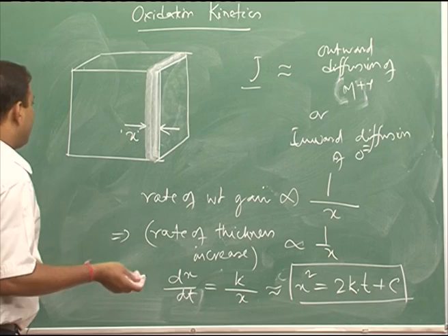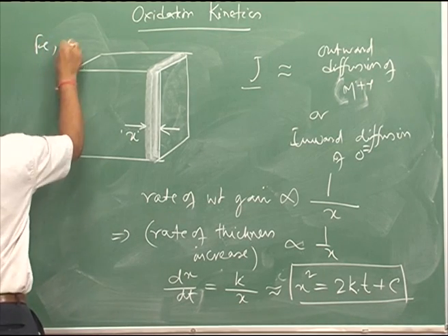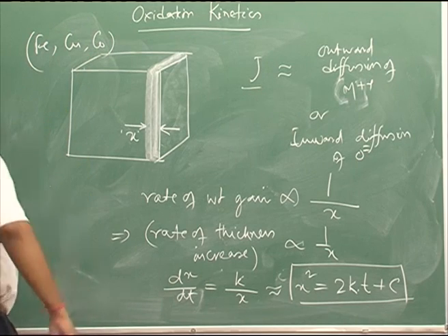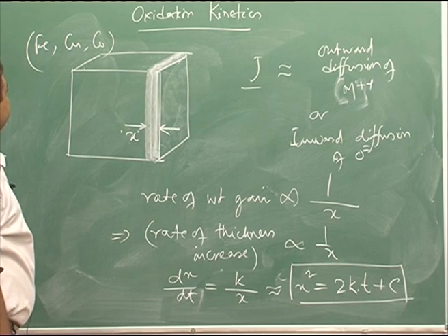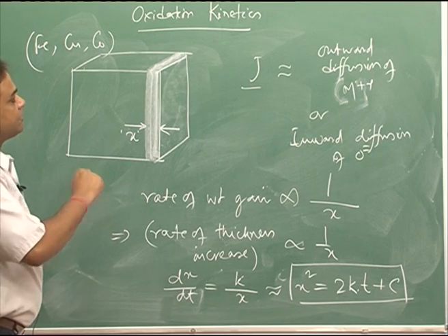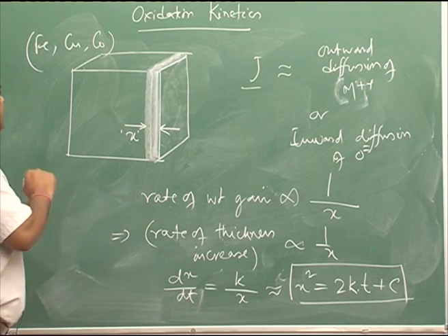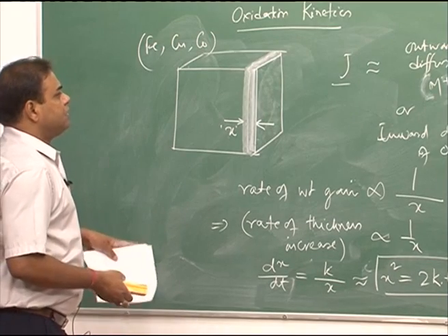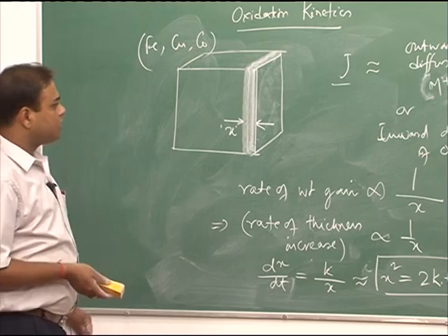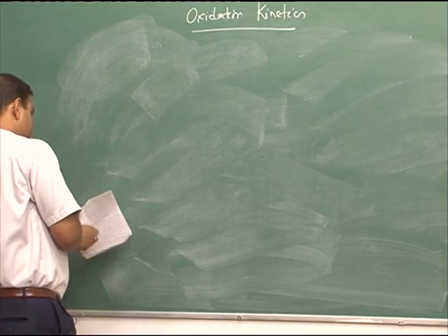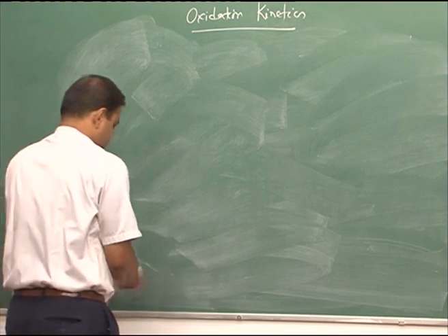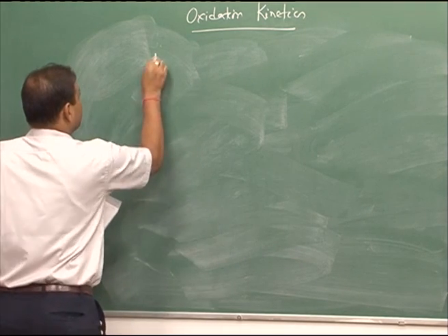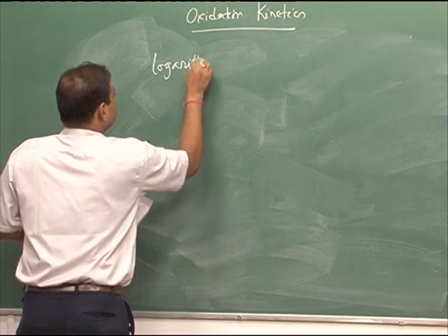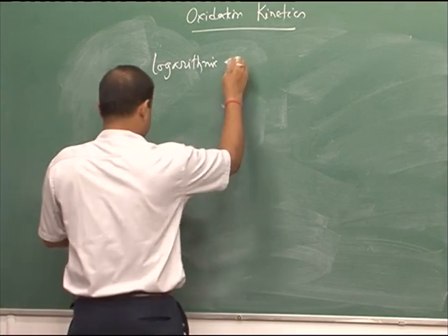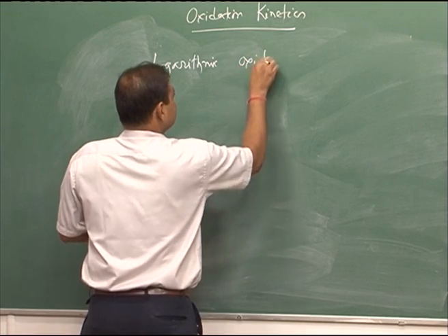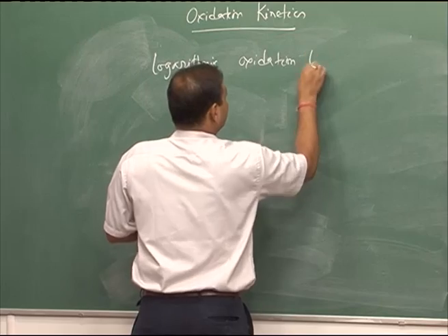So, this is a simplistic approach to prove the parabolic oxidation law, and where we can find this parabolic oxidation law? For example, in case of iron, copper, cobalt, all those cases at high temperature, we always find that the oxidation law is governed by the parabolic rate law. We can also find the oxidation law obeying a logarithmic expression. So, we can also have a logarithmic oxidation law,